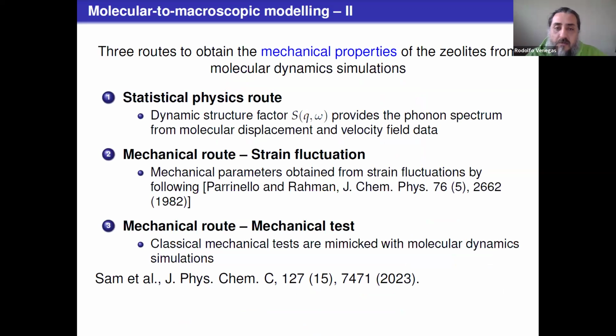We have published this first study in the Journal of Physical Chemistry C. And in that particular paper, we considered three different routes. One of them is what we call a statistical physics route. In all three, the aim is to get the mechanical properties of this zeolite structure. In the statistical physics route, what we do is get molecular displacement and velocity field data by solving molecular dynamics models. And then we fit this data to a dynamic structure factor, S(Q, omega).